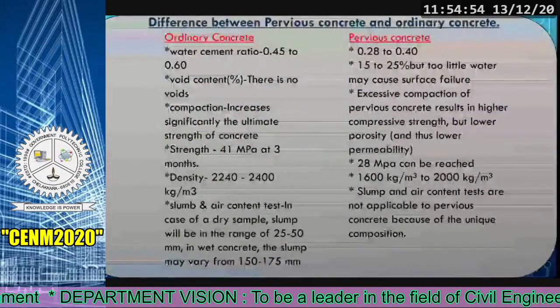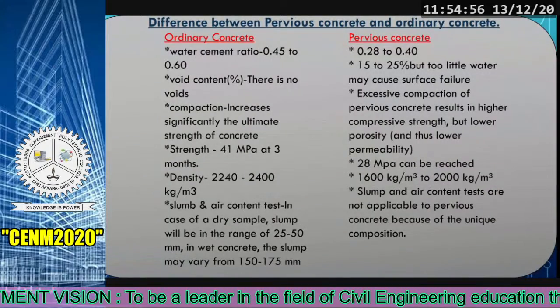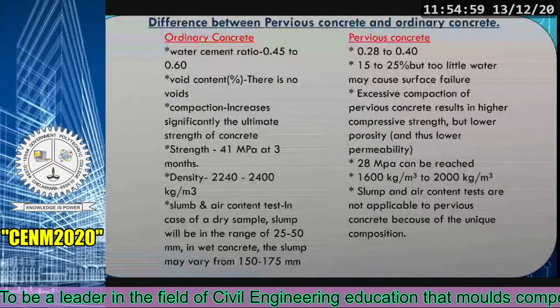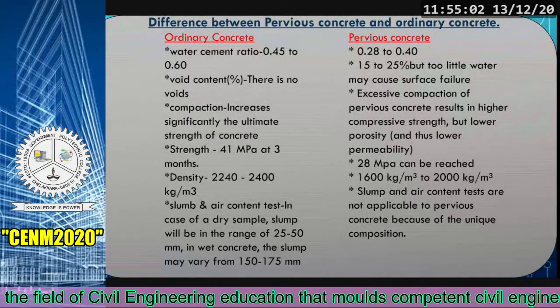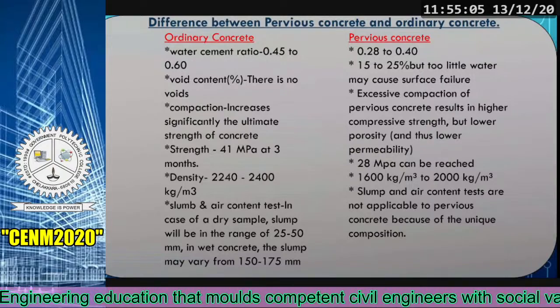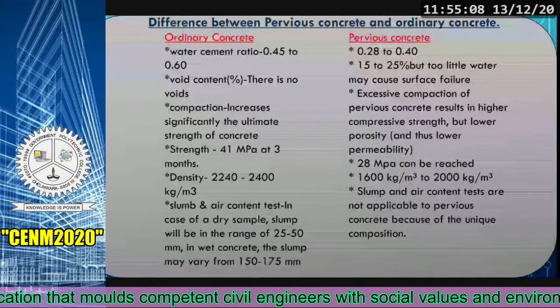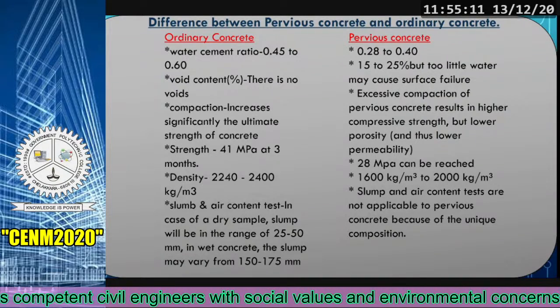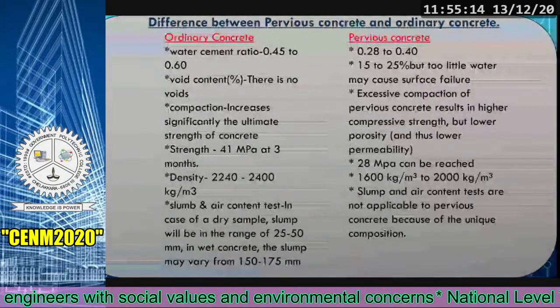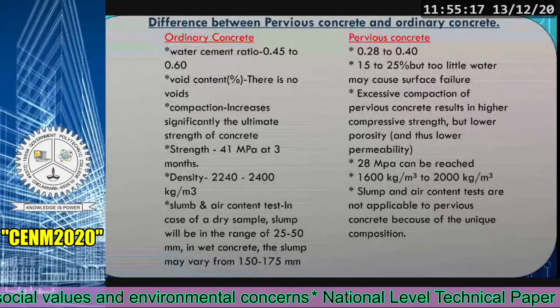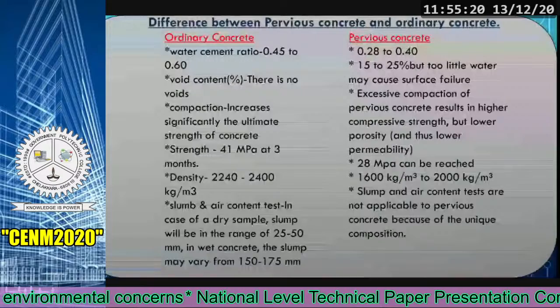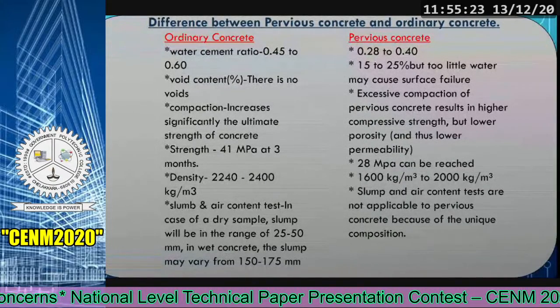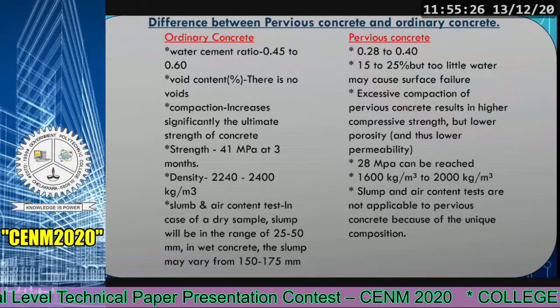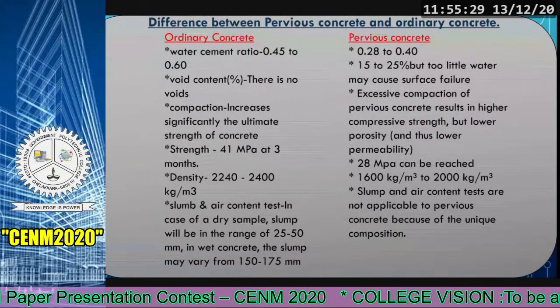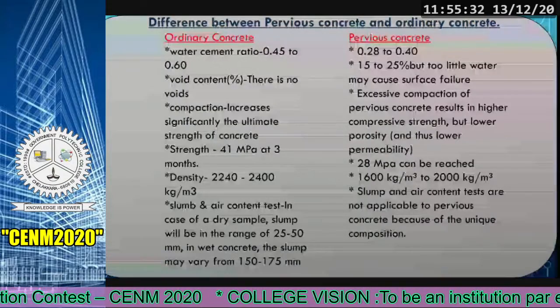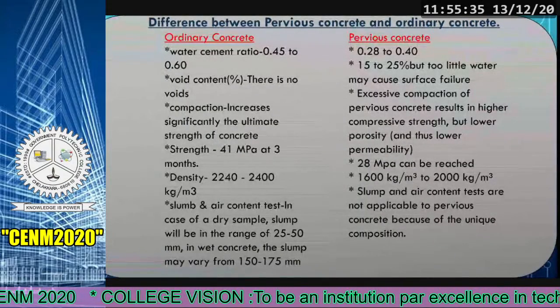Here, you can see a difference charted between pervious concrete and ordinary concrete. Water to cement ratio in ordinary concrete is 0.45 to 0.60, whereas in pervious it is 0.28 to 0.40. Coming to void content, there are no voids in ordinary concrete, but there is 15 to 25% in pervious concrete. In case of compaction, it increases the ultimate strength of ordinary concrete, while excessive compaction in pervious concrete results in higher compressive strength but lower porosity, and it also lowers the permeability.